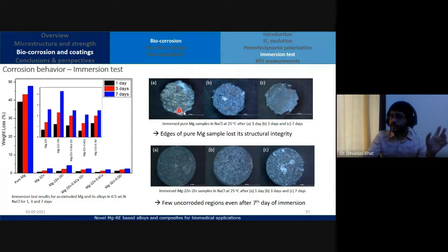You can see here the pure magnesium. Just after 1 day in sodium chloride, it looks like this. After 3 days, and after 7 days, you see what happens, right? The structural integrity is lost. Whereas for the alloys, you see here, not so bad, right? It degrades, of course. We want degradation, right? It's not like we want a completely inert material. We want it, but it shouldn't be as high as that of magnesium.